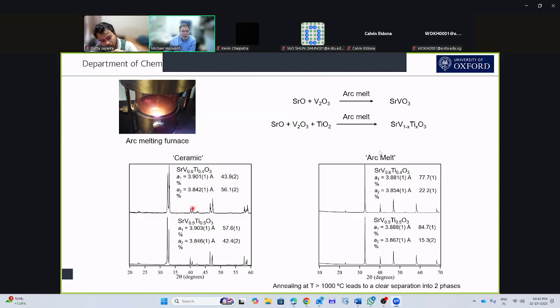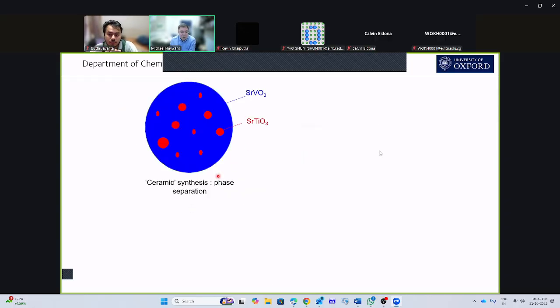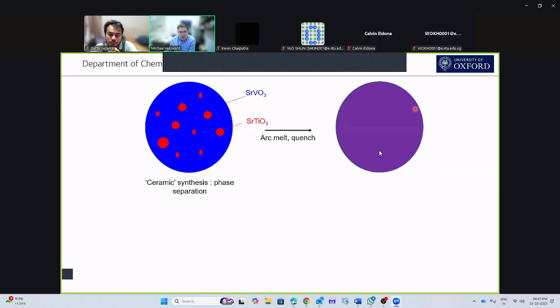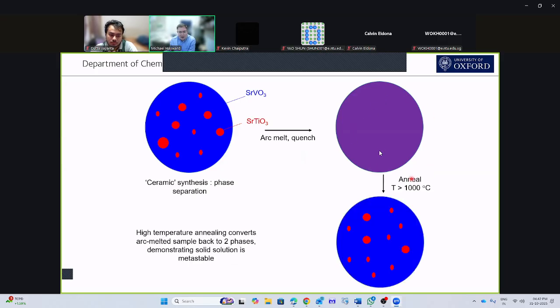And we can see why that is by thinking about what we're doing in the arc furnace. So in the arc furnace, we could take a ceramic product where I've got a mixture of strontium titanate and strontium vanadate. And when I melt them and quench them, I get like a frozen liquid where the titanium is randomly distributed through the solid. But if I anneal them, I'm allowing the system to have enough energy that the titanium and vanadium can separate out again. So it shows that this titanium doped strontium vanadate is a metastable phase.